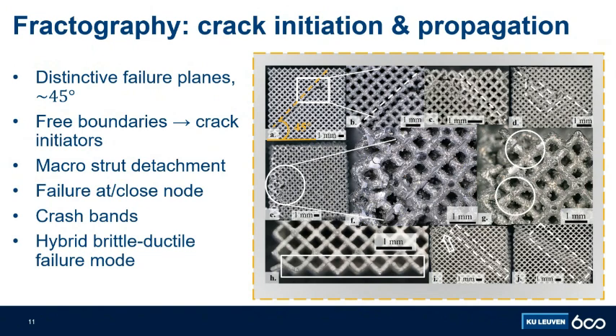This is where maximum bending moments are created according to the beam theory, and this is also where we have a lot of geometry changes due to the waviness and the change in diameter within the struts. Crack bands are formed both in the as-built and the heat-treated category, and there is an observation of a hybrid brittle to ductile failure mode.